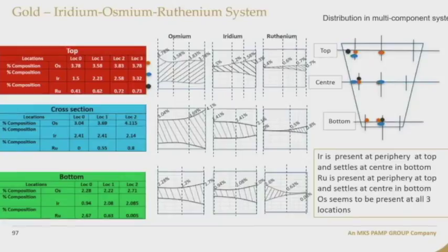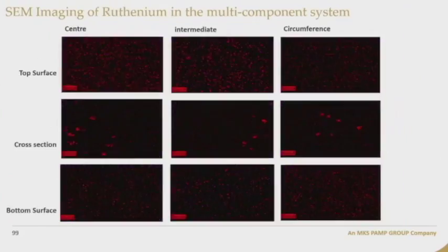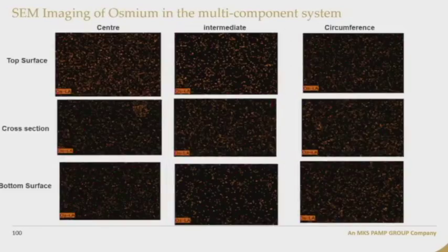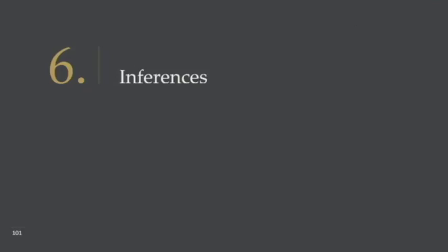In a mixed system, iridium is present at the periphery and at top and settles at center in the bottom. But ruthenium, as our reading of XRF and individual metals showed, is present more at the periphery while it should be at the center in the top. And it also settles at the bottom, probably because of the mix. And osmium seems to be present in all the 3 locations. So you can see even ruthenium in the mix is also forming clusters. Osmium is in a dense form.